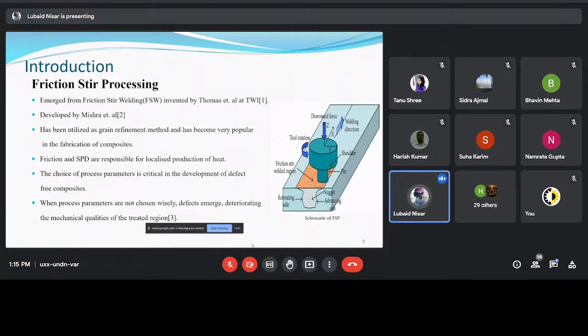In this process, basically a moving and rotating non-consumable tool is inserted onto the specimen, and the tool translates along a particular direction with constant traveling speed. When the tool translates and rotates, heat is produced at the expense of friction between the tool and the workpiece. The friction and severe plastic deformation are responsible for producing localized heat, which leads to the softening of workpiece material and eases the motion of material from the front to the back of the tool pin. This process leads to microstructure modification and results in removal of defects caused by pores and cracks during casting.